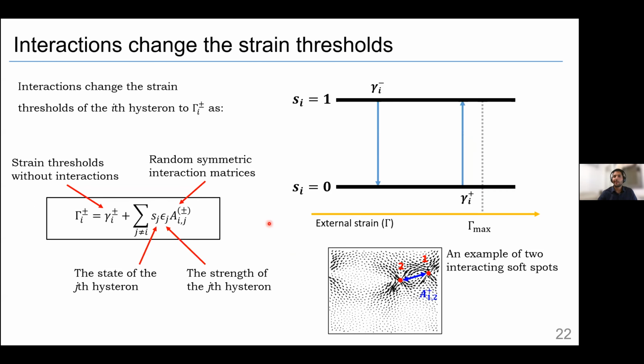So in order to get something multi-periodic, we introduce interactions. How we do it, you take this gamma plus and gamma minus and add some interaction parameter. What you can see here is just a displacement field of two soft spots. So you can see that 1 and 2 interact via these quadrupolar displacement fields. So we have here some random interaction matrix, this is Aij. And we have a strength factor that we give each hysteron to represent its size. And it also depends on the state of the hysteron. So if it switches to 1, it adds it. If it switches back to 0, it subtracts it. And we have a new gamma plus and gamma minus.